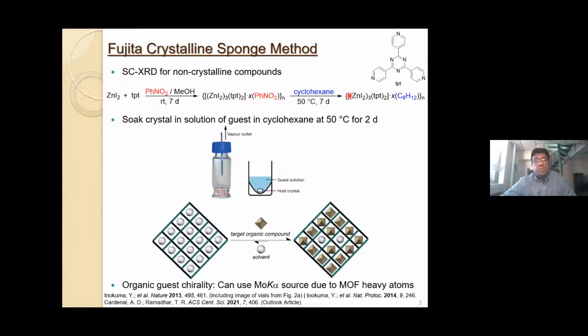What you do next when you want to do the crystalline sponge method is that you take one of these crystals, you put it into a vial, you have the target compounds that you want to analyze in microgram to nanogram quantities, solvated in cyclohexane with a little bit of halogenated solvent to facilitate solvation. And then you have like a 50 microliter solution of that, you add it to your crystal, you seal the vial up, you put a needle through it, and then you stick it in an oven at 50 degrees centigrade for 2 days. And then what happens during that period is that the solvent's going to slowly evaporate, and the